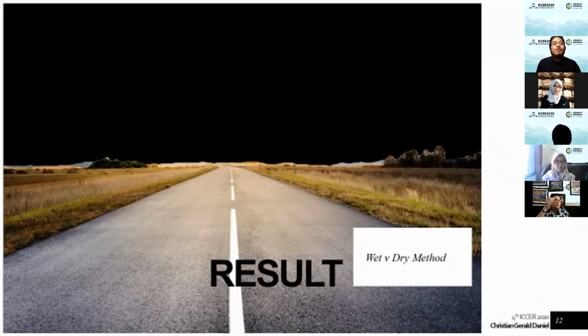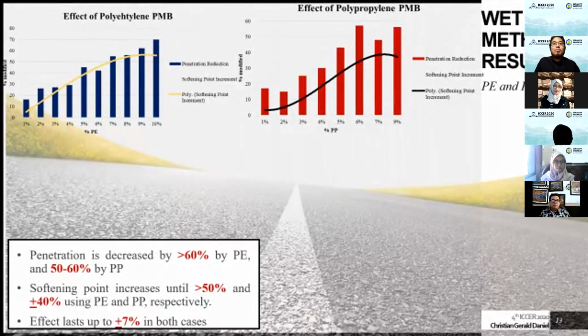And the question is, what are the effects of both methods? Let's dive into it. The first one is the wet method. Using polyethylene and polypropylene, we can see that the penetration is decreased by around 60% by PE and PP respectively. Both indicate quite similar performance. Also with the softening point, PE modified bitumen is maybe more beneficial, but it's just a slight improvement, more than 50% and 40 to 50%.